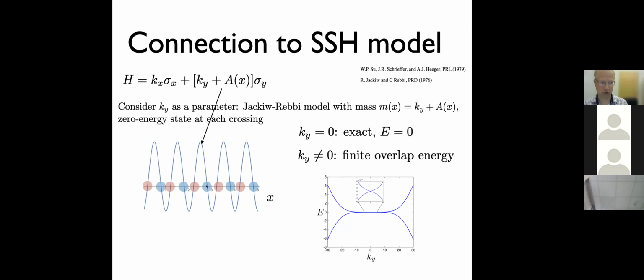Because it oscillates, there is a zero energy state at each crossing point where it changes sign, like in the Jackiw-Rebbi model. The flat band consists of these states, and the finite dispersion comes from the overlap energy between the various zero energy modes. So if ky is equal to 0, this is exact and the energy is 0, but if you have a finite ky, there is finite overlap energy, but this overlap energy scales exponentially with the amplitude of this A.